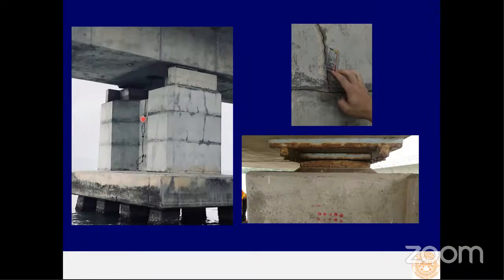after we constructed and used the bridge, we found some corrosion problems. We found cracks initiating around the pier, and that is due to corrosion of the reinforcement inside that caused the concrete to break out. Not only the pier caused problems, we found the bridge accessories like the bearing here. At that time, we didn't have the technology to use a special painting system for the bearing. We used probably just regular steel, and we used some protective coating that was not very strong and not very tough for sea water. So after 5 years, let's say 7 to 10 years, the bearing started to form corrosion like that.